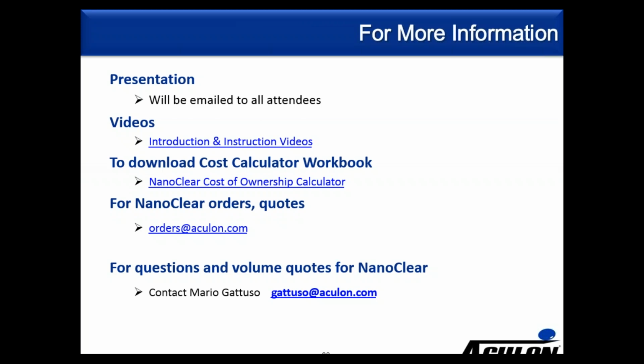So next question that's come in is, do I need to use water after the cleaner? So NanoClear is a part A and part B paste treatment. So there's a cleaning step, a water rinse, and then the NanoClear is applied. So the cleaner contains salts which do need to be washed away. So you can't just use a water wipe, and you certainly cannot skip rinsing the cleaner off. It needs to be rinsed off with running water. So please be sure to rinse off the stencil with running water, allow it to dry, and then apply the NanoClear coating.